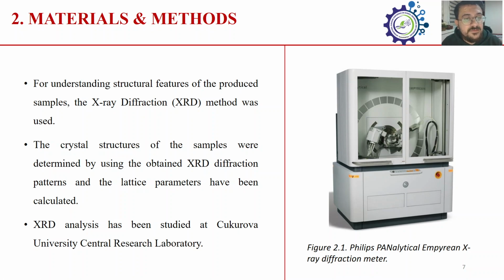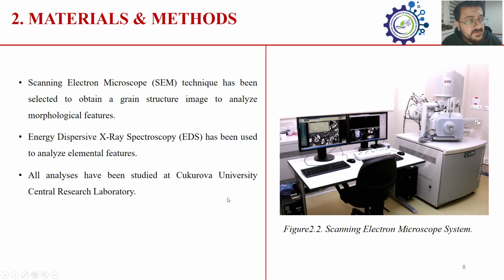For understanding structural features of the produced sample, the X-ray diffraction method was used. The crystal structure of the sample was determined by using the obtained XRD diffraction patterns and the lattice parameters have been calculated. Scanning electron microscope technique has been selected to obtain a grain structure image to analyze morphological features. All analyses have been carried out at Çukurova University Central Research Laboratory.